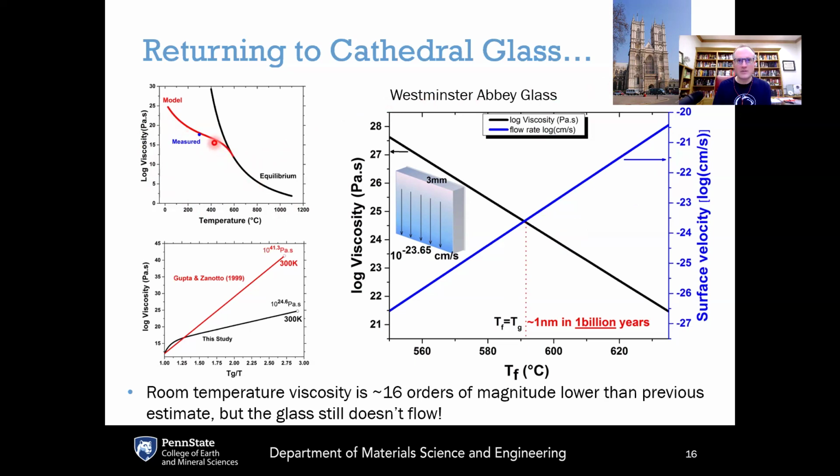We had a very patient measurement of viscosity here. This is the equilibrium viscosity in black, and then the measured viscosity of the non-equilibrium glassy state as the blue point shown here, close to 10 to the 18 Pascal seconds. So this measurement took a very long time. And you can see excellent agreement here between the measured result and the model predicted result.